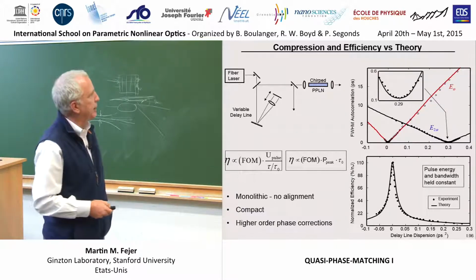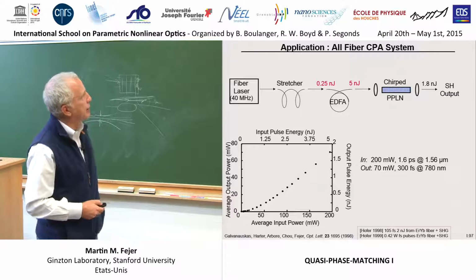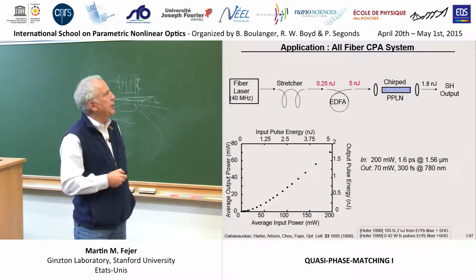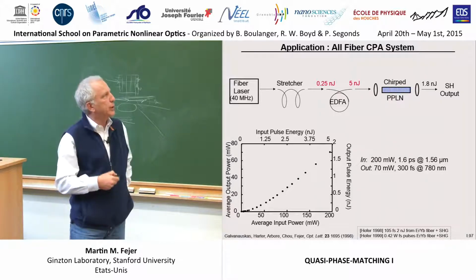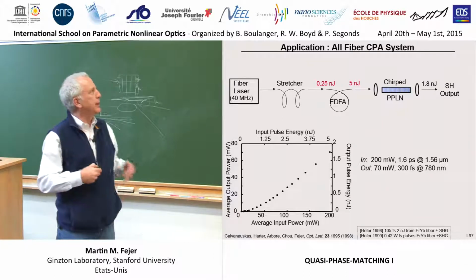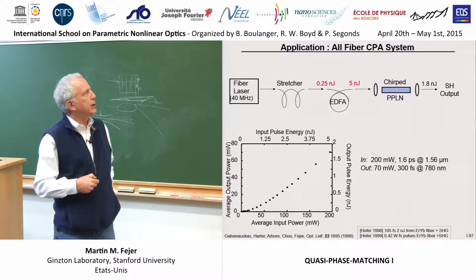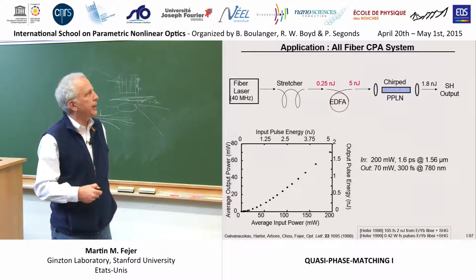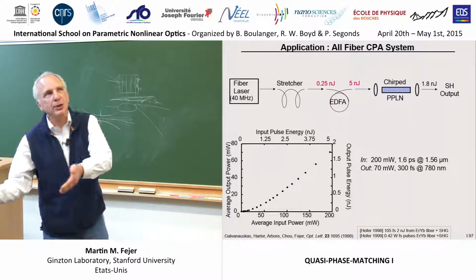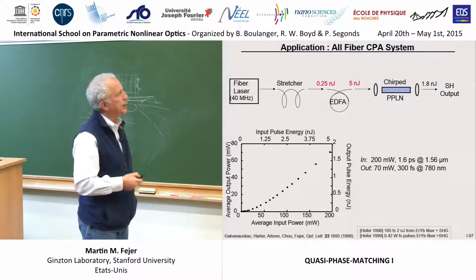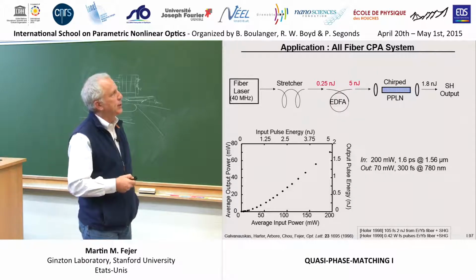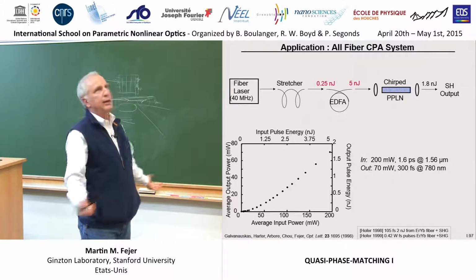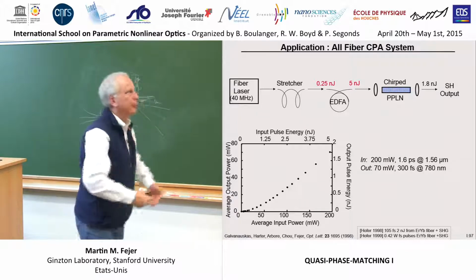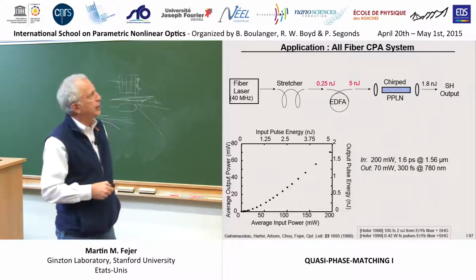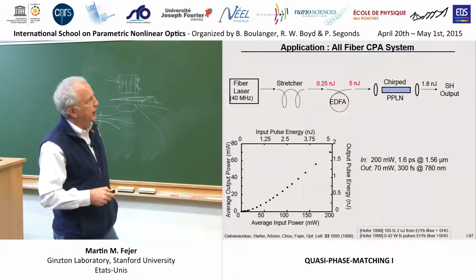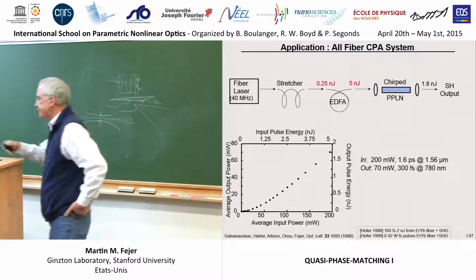So let me finish up with just a couple more points. This thing was used, in fact, in an all-fiber chirped pulse amplification system: laser oscillator, stretching fiber, erbium amplifier, and then, since the goal here was to make a 780 nanometer source, sort of a Ti:sapphire replacement, using this chirped periodically poled crystal eliminated the requirement for a separate pulse compressor. You could do the harmonic generation and the pulse compression in that one chip.